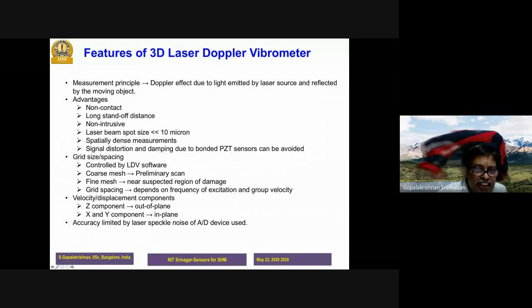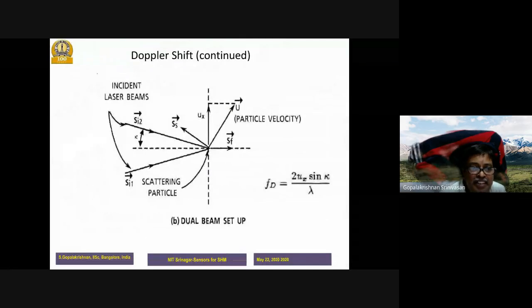So the advantage here is non-contact. You can measure what is going on in the structure from at least 10 to 15 feet distance, and the laser beam spot size is less than 10 micron, and you can get spatially dense measurement at micron size. Signal distortion and damping due to bonded sensors can be avoided. It can have grid spacing. You can monitor small regions, large regions. No disassembly, for example in an aircraft, is needed. You can get the velocity components in all three directions. Okay.